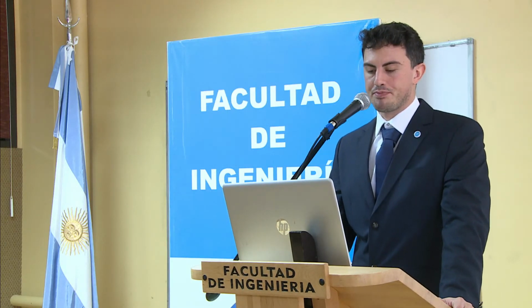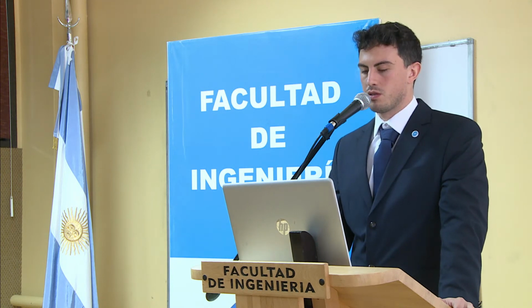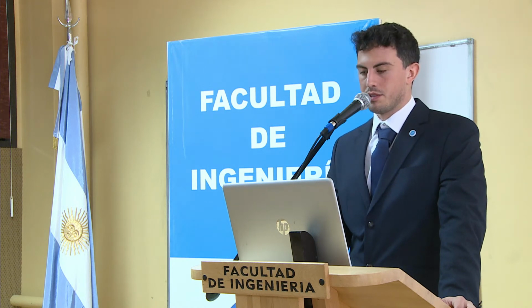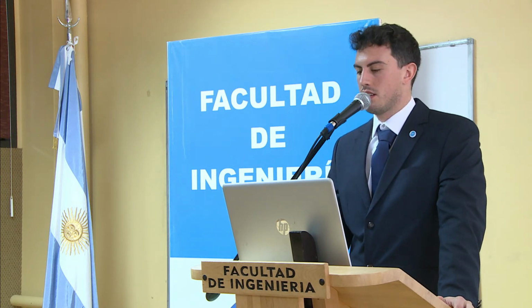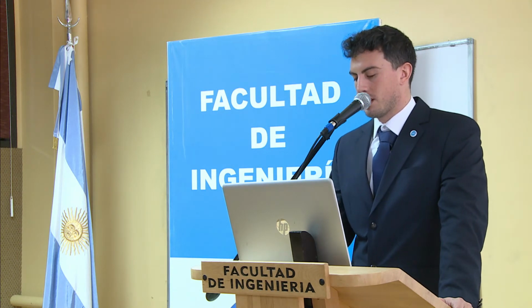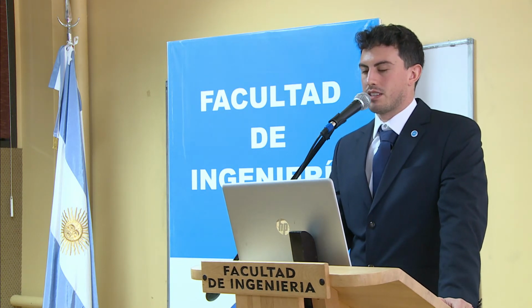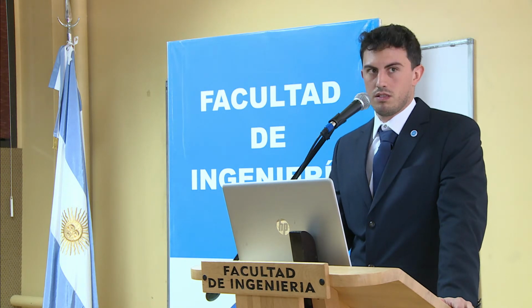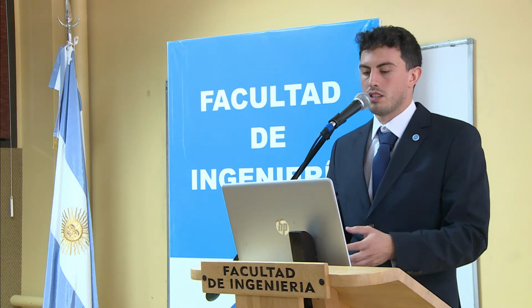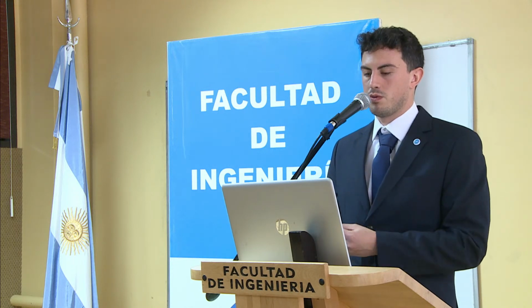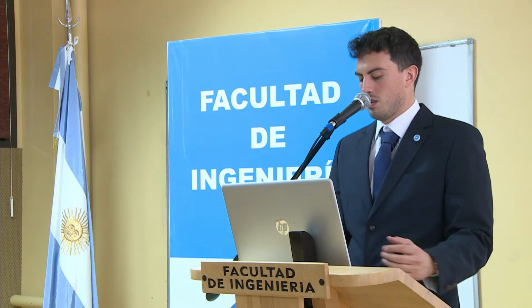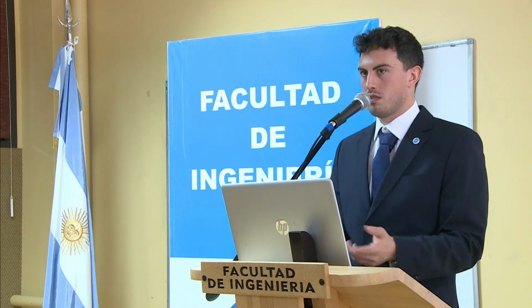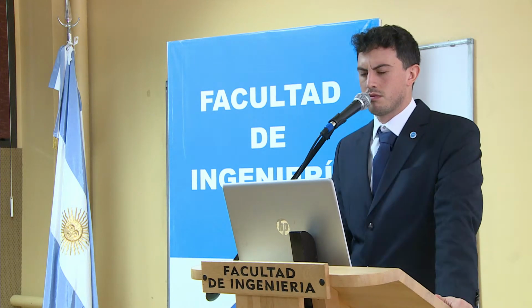Okay, so firstly we used 20 degrees Celsius to cure the samples because it was the easiest way that we were using in the lab, and it's already very standardized. But as we saw that carbonation was not affecting these specimens, it was not a large carbonation, and we wanted to have the samples fully carbonated, we did a second curing method, which is the one at 90 degrees, in order to.